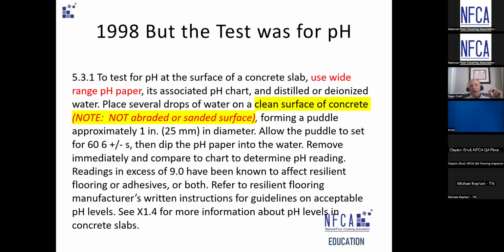A couple of things I want to point out too is that the standard says a clean concrete surface. A lot of people, because they were doing the 1869, which required abrading the surface of the concrete, would abrade the concrete and test where they abraded. That was never correct and never part of the standard. And that also gave a lot of high readings, because once you remove that carbonated layer, you expose the higher alkali material below, and it wasn't unusual to get automatic high readings.